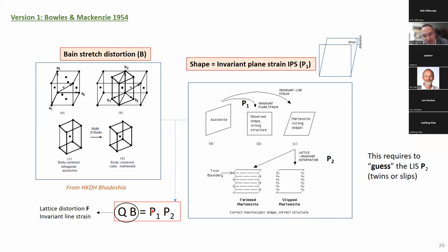And it's the same here. If you combine an IPS with a lattice invariant shear, you also have an invariant line strain. So you can put that into coherency. The only thing you have to do is to guess what this lattice invariant shear is. It can be glide of dislocations, it can be mechanical twinning, whatever. That's maybe the problem of this version of PTMC.